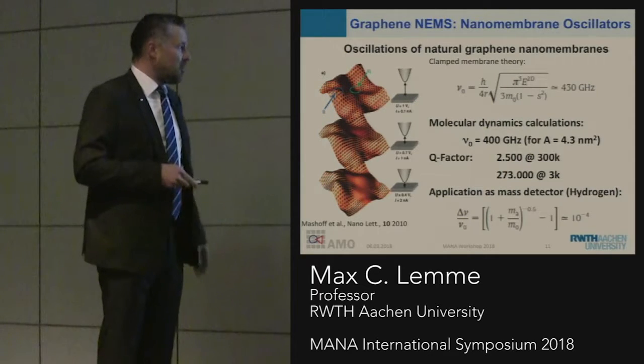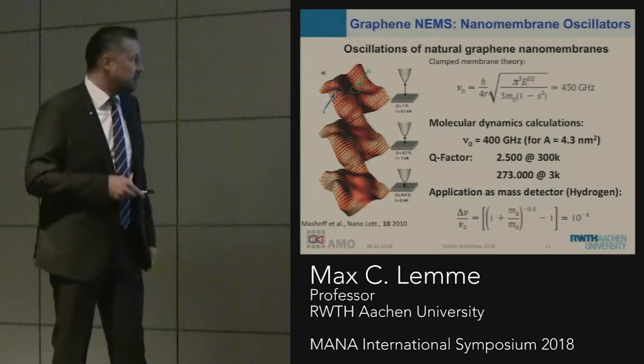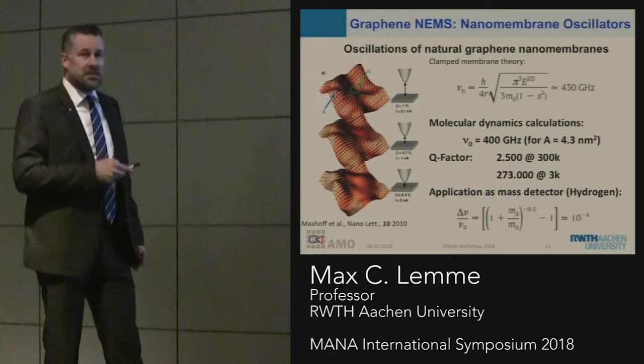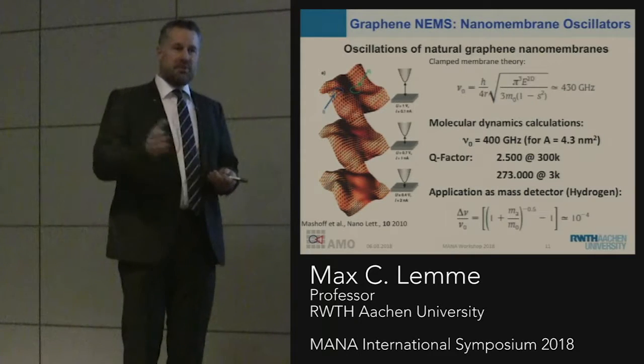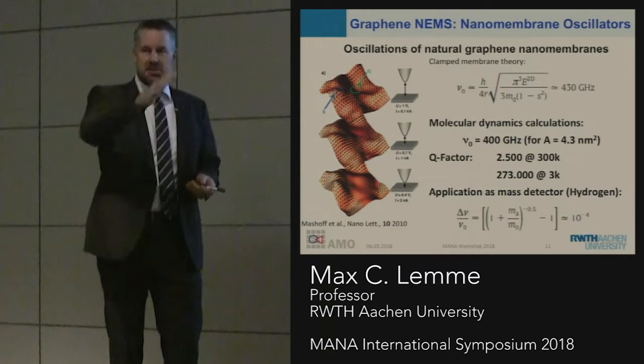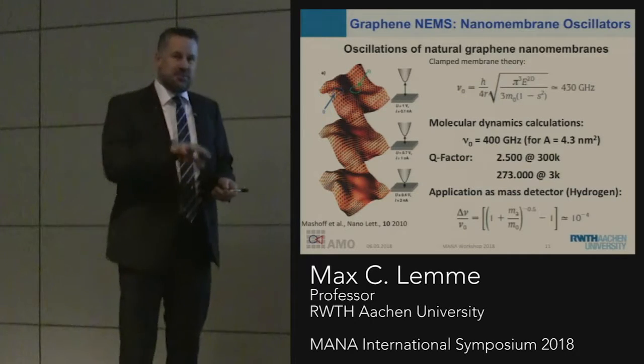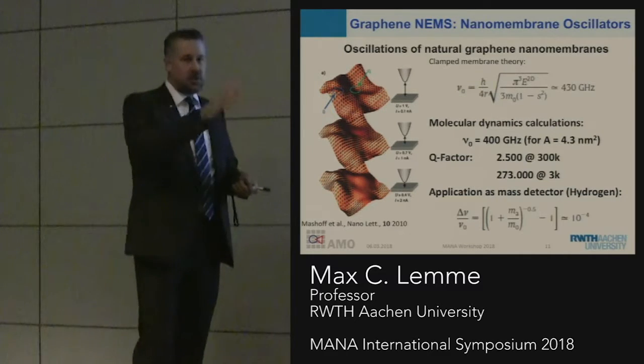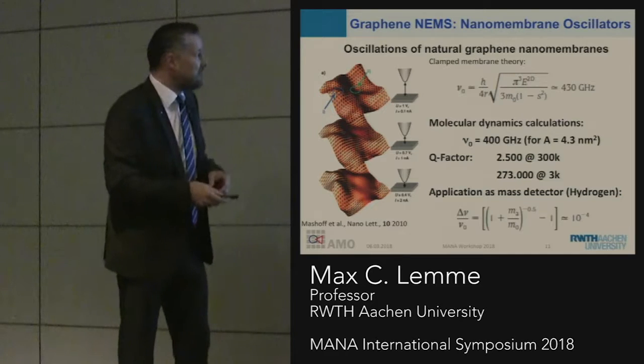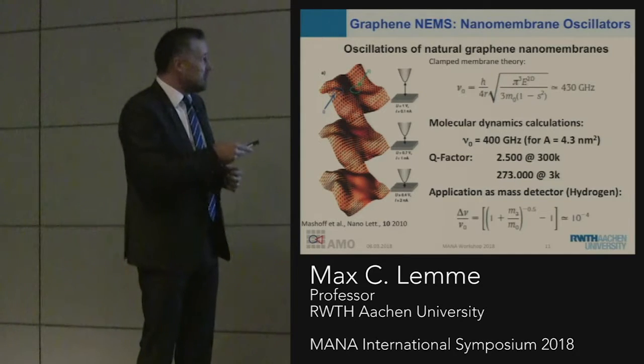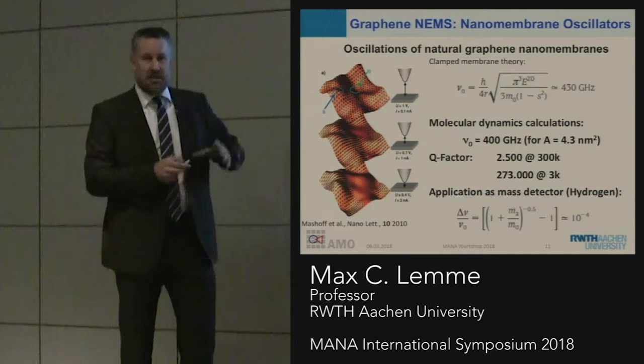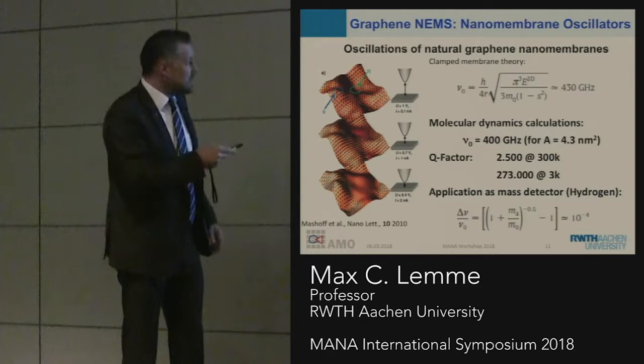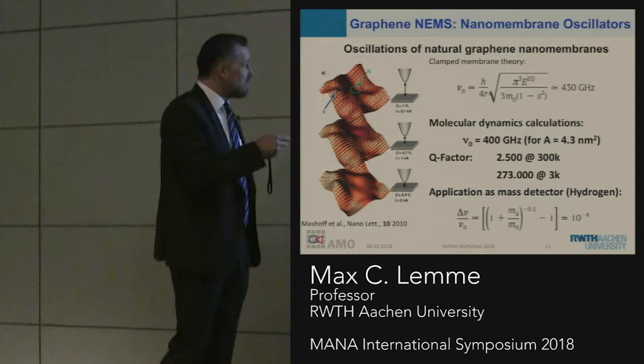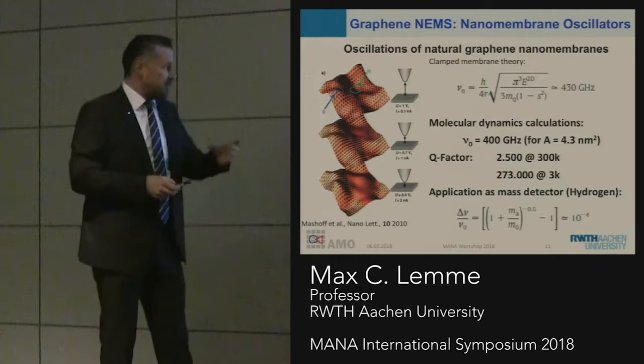This is one of the earlier works we did in Aachen with the Morgenstern group. We looked at graphene on a silicon oxide surface. When you put graphene on a silicon oxide surface, it is corrugated, and the roughness of the silicon oxide along with the corrugation in the graphene leads to natural nanomembranes that can occur randomly on the surface.